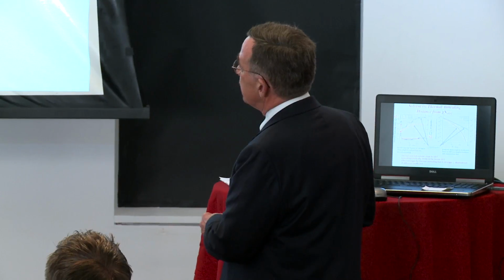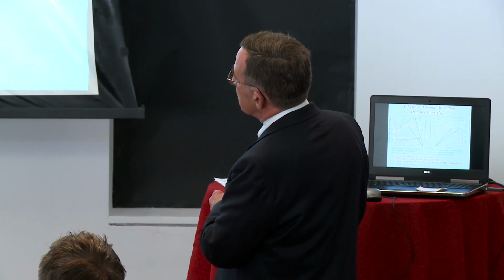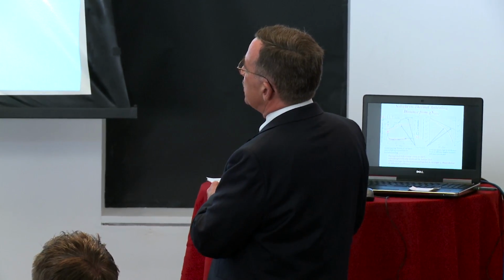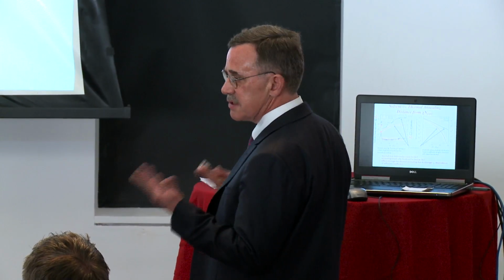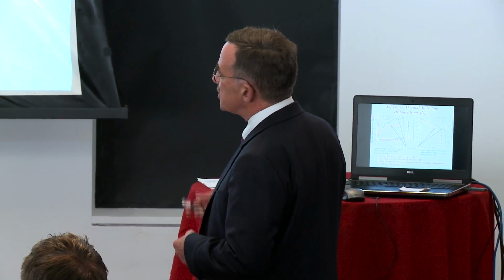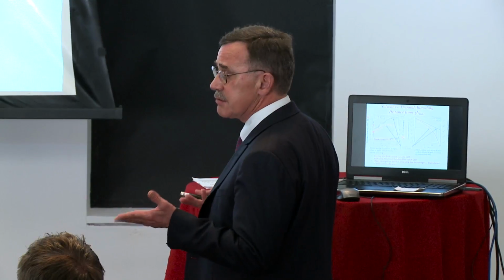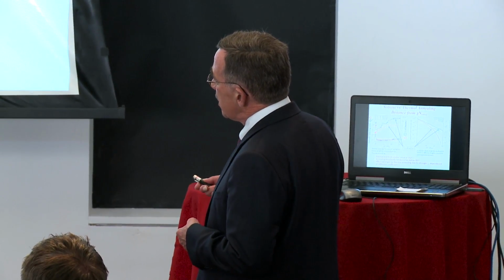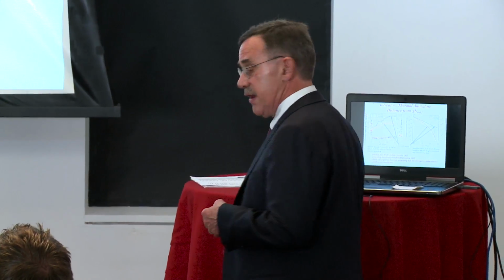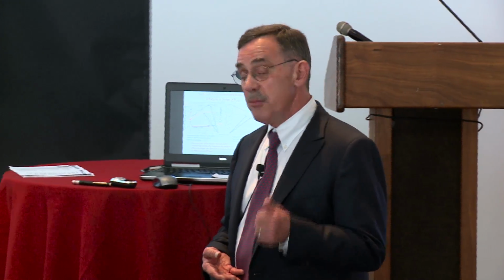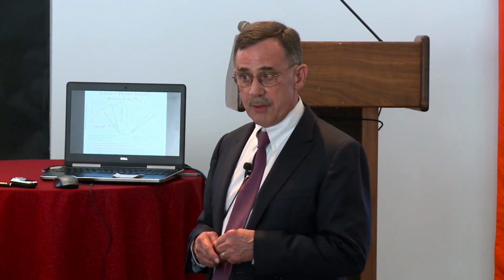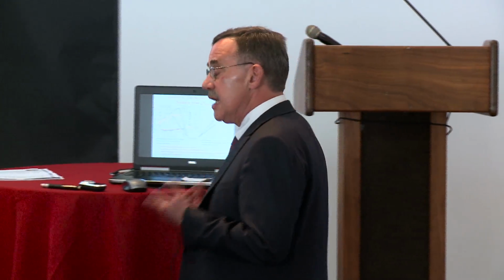In the case of the thermal and solvent annealing, this is what we saw before. We see the period will begin to increase. We start to cool, and then we get to a point where the system starts to vitrify. And it's at this particular point, when the system begins to vitrify, that we start to introduce disorder into the system. With thermal annealing, we can do a similar type of experiment. And what we find is that the disorder we place in the film when it's thermally annealed is far less. But we sacrifice because it's a little bit slower. So what this is telling me is that, yes, we can get long-range lateral order, but if we can do it by thermal means as opposed to solvent means, we're a lot better off.